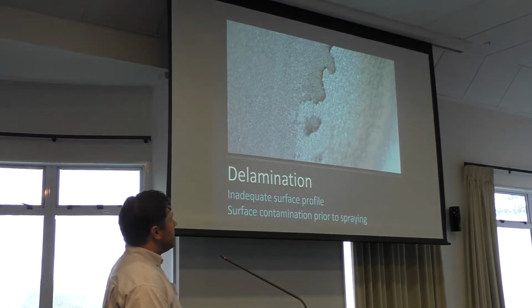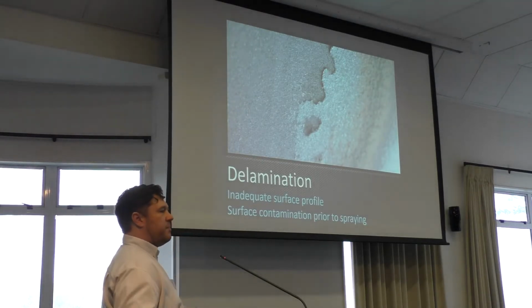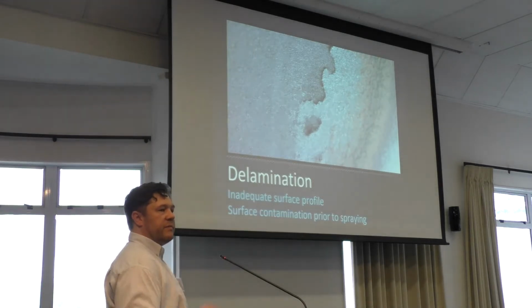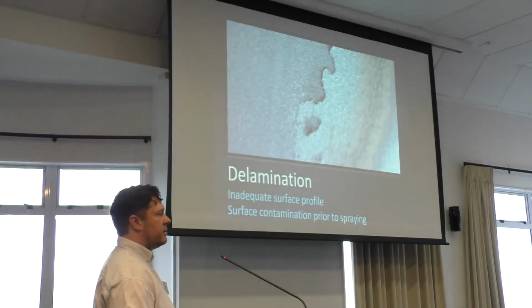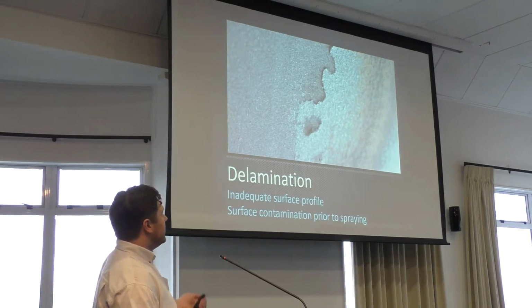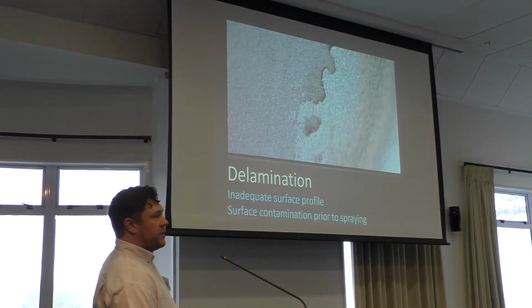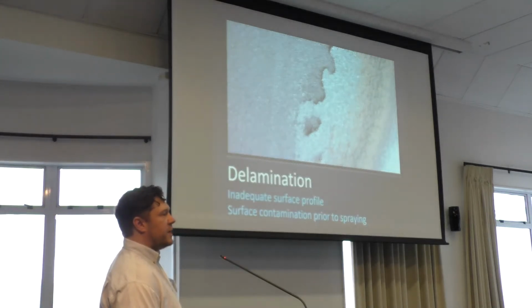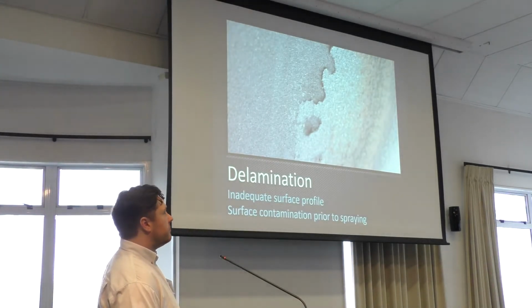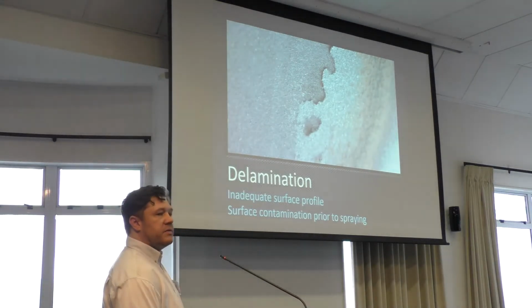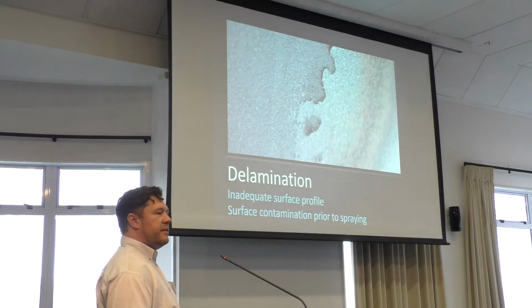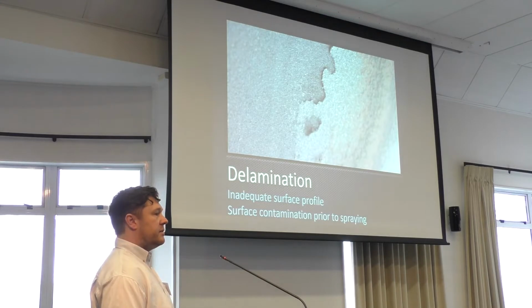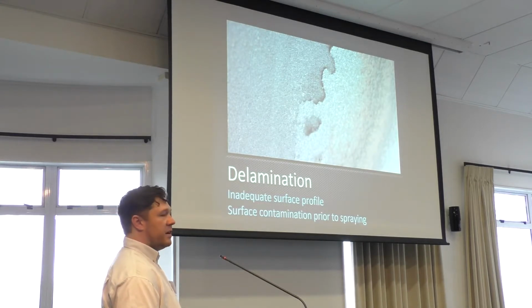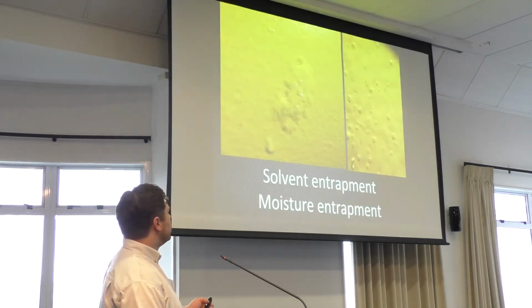And they've been feathering that. They're trying to recoat a weld joint. So they're feathering the old coating out to put some more metal spray on the weld. And it started picking up when they were blasting it. And really, it should be extremely hard to blast zinc off. It should be well and truly on there. So that measured at about 25 to 35 microns when I was checking the surface profile. ASNZ 2312 says we need a minimum of 50 before we can continue with the job. So it's a lesson in why we need to check our profile and not just trust how it feels with your thumb.